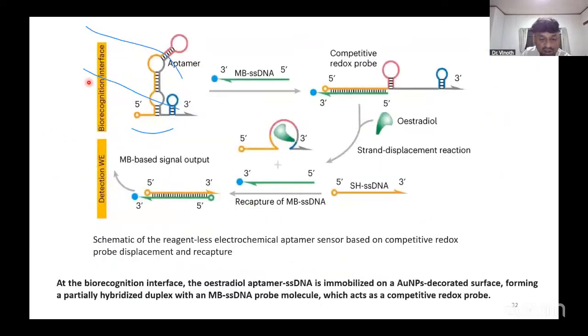Here is the simple mechanism of the DNA aptamer, a single-stranded DNA estradiol aptamer at the gold electrode surface. On the aptamer, we have a 3' and 5' end, with methylene blue as the redox probe. With the displacement by estradiol, the Au-S bond can be formed, which can be captured at the electrode, producing the signal output. Then methylene blue can be released. At the biorecognition interface, the estradiol aptamer DNA is immobilized on the gold nanoparticle surface, forming a partially hybridized duplex with the methylene blue single-stranded DNA probe molecule, which acts as a competitive probe.